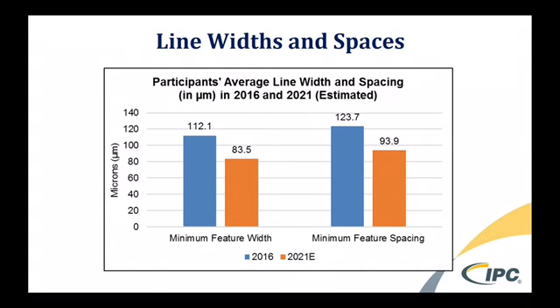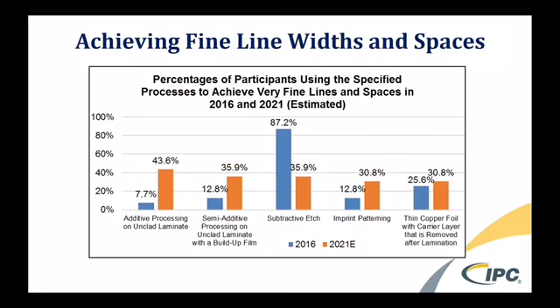With this goes line widths and spaces. When you have increased densification, you're going to see smaller holes, higher aspect ratios potentially. At the same time, you have to add more wire density if you're going to reduce layer counts and truly make HDI an effective enabling technology for your business. And you can see how the feature widths and spacings are decreasing, and that of course is going to be driving more and more investment into laser direct imaging and surface preparation processes and technology.